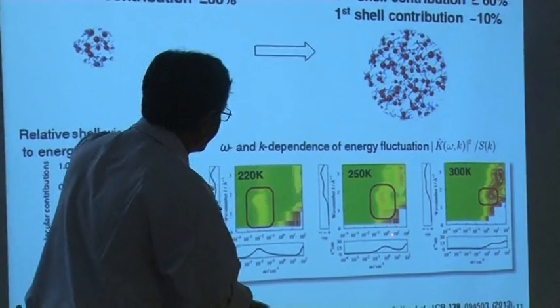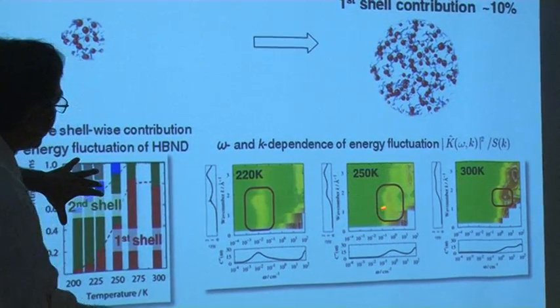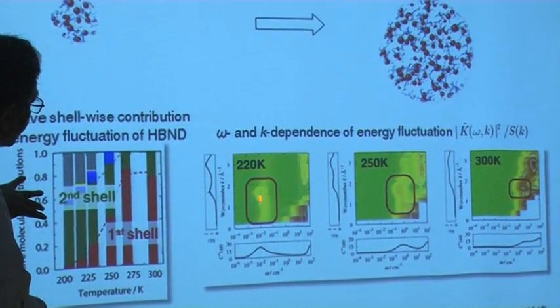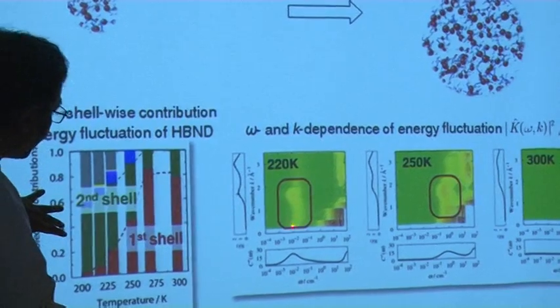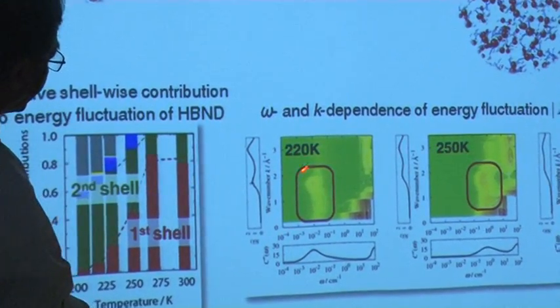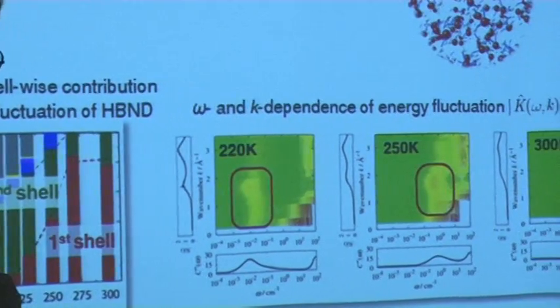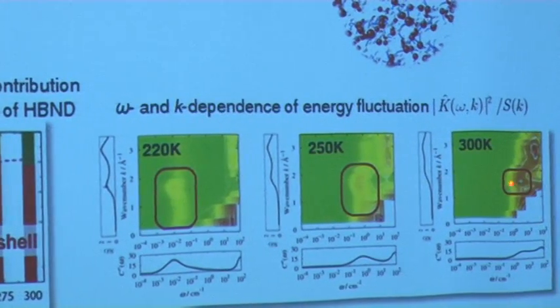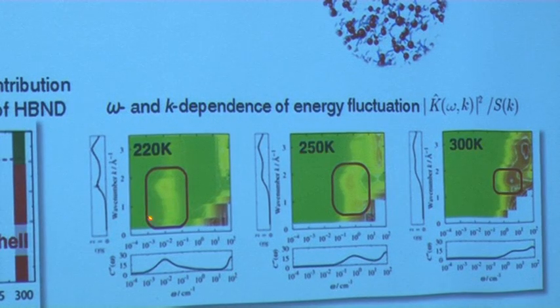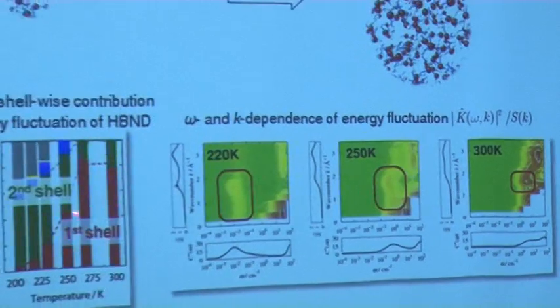So as you lower the temperature, low frequency and longer correlated fluctuations come. Look at this peak. Here everything is localized. Here they are delocalized. Here they are of the nearest neighbor level. Here, up to 6 nearest neighbors, the fluctuations come. And this is shown here.